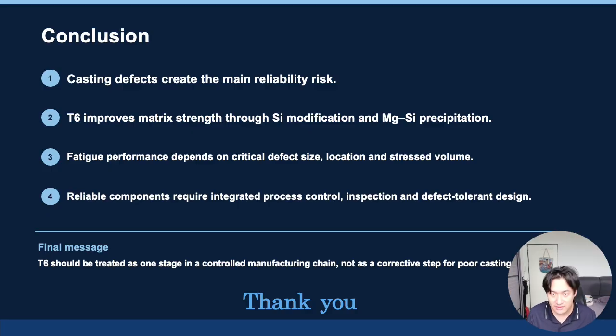To conclude, the Al-Si-Mg alloys gain their performance from the full manufacturing sequence. Casting defects create the main reliability risk. T6 improves the matrix through silicon modification and Mg2Si precipitation, but it cannot remove pores or bifilms. Fatigue performance depends on the critical defect and stressed volume. Therefore, reliable components require the integrated control of melt handling, filling, solidification, T6 treatment, inspection, and defect-tolerant design. So thank you, professors.